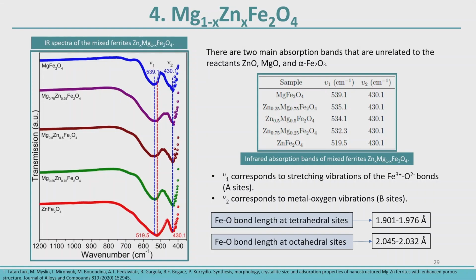Broadening at least. And it for sure is because you have oxygen and do not have iron linked to it, and it changes depending on the environment. Because it happens, for instance, in silicon, there is something similar, where when you have vacancies in silicon, you can see the size of the vacancy by the frequency. Because the frequency changes when you have more free space around the, let's say, the harmonic oscillator, okay?